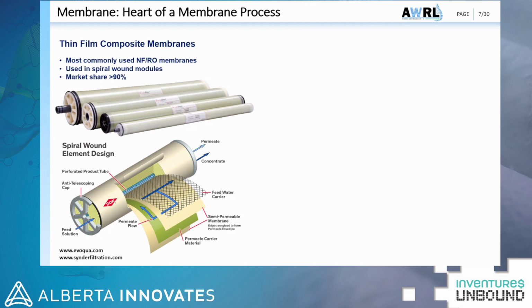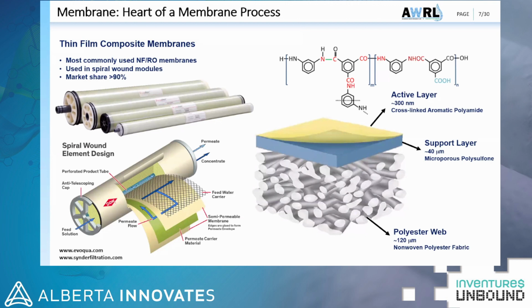Now, if you look at the TFC reverse osmosis membrane more closely, you can see that it has three layers. The top layer, which is the most important layer and is called the active layer, is polyamide with a thickness around 300 nanometer. The middle layer is a microporous support layer, which is in fact a 40 to 50 micron polysulfone UF membrane. And the bottom layer is a polyester fabric, which provides mechanical strength to the membrane.